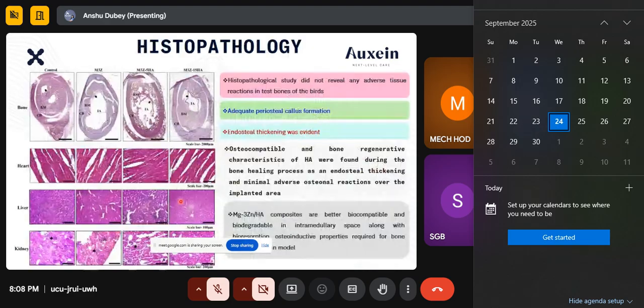So after that, the two birds were euthanized. So we checked the histopathology, and we saw that the bone was growing fast, and there was no problem in the heart, in the liver, even in the kidney. So the bone growth was there around this, and it was more in the case of the implant with 15% hydroxyapatite. So the composite did well, and with 15% hydroxyapatite, it supported the bone growth.